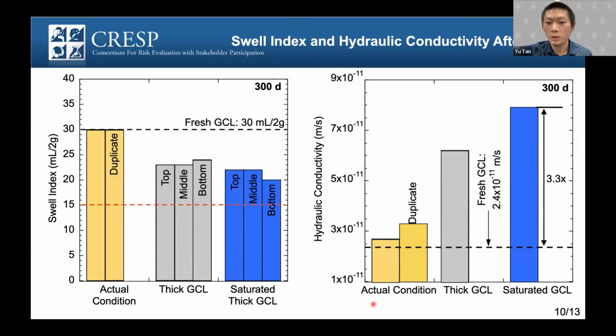For the actual condition, the hydraulic conductivity of the GCL is comparable with the fresh GCL, 1 or 2 times 10⁻¹¹. When we go to the thicker GCL, the swell index decreased a little bit, so hydraulic conductivity increased a little bit. And for the saturated GCL, the worst case in our study, the hydraulic conductivity shows the highest increase, but the increase is only 3 times. This is not a very high increase in hydraulic conductivity.